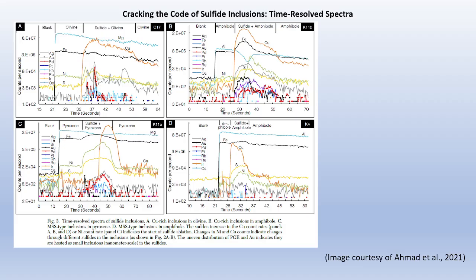So what's unusual about this dataset? It's the level of detail. We are not just identifying which elements are present. We are watching in real time how metals like gold and palladium partition as a sulfide melt crystallizes deep in the crust. These inclusions capture the dynamics of sulfide saturation at sub-second resolution, and that's critical because it shows us how early sulfide phases can strip copper, gold, and PGEs from magmas long before they ever have a chance to rise and form porphyry deposits at shallower depths.